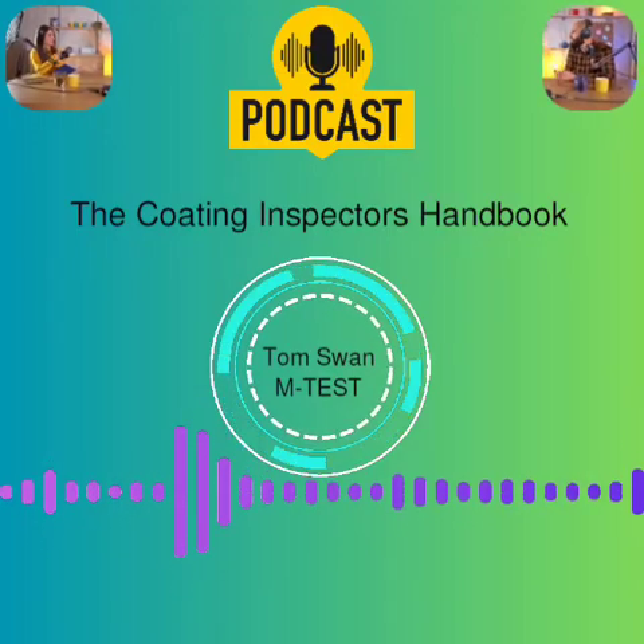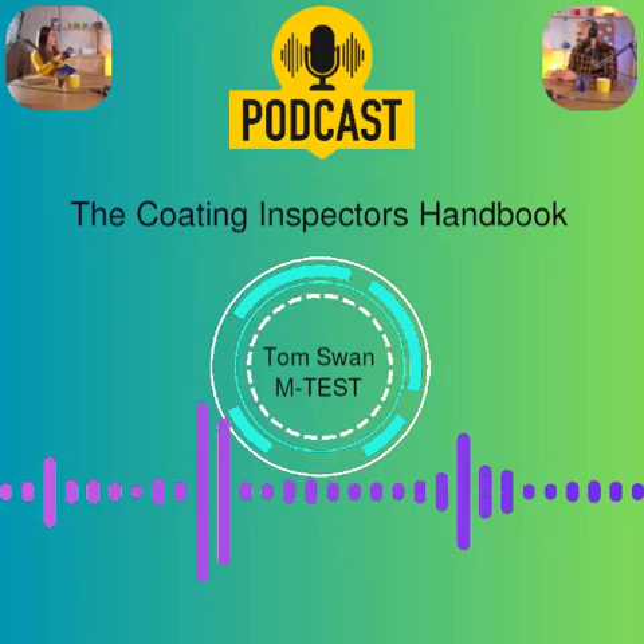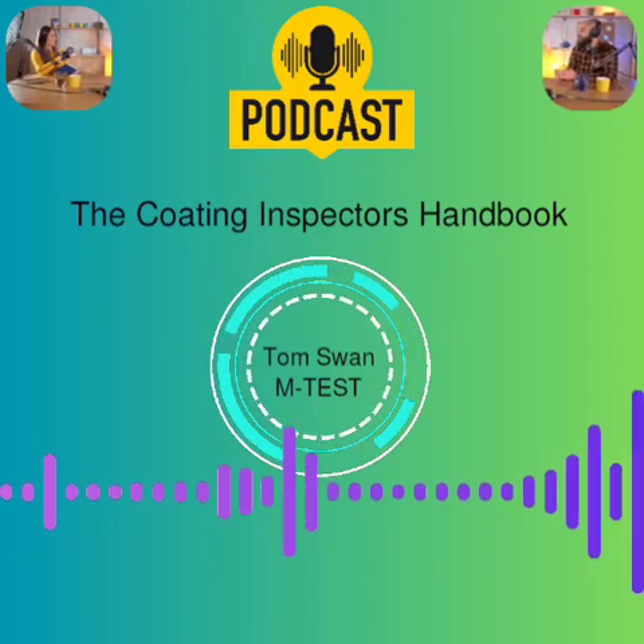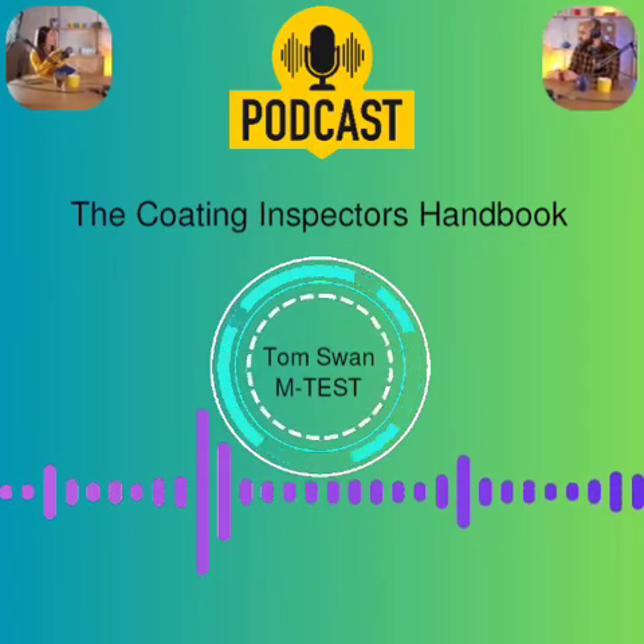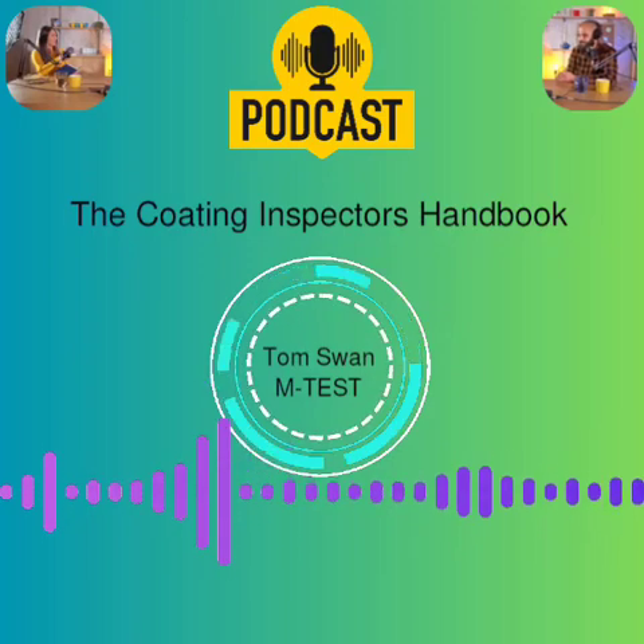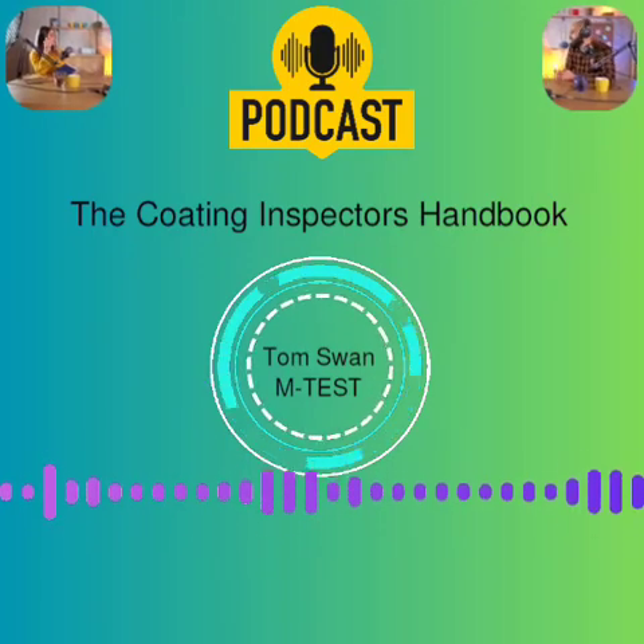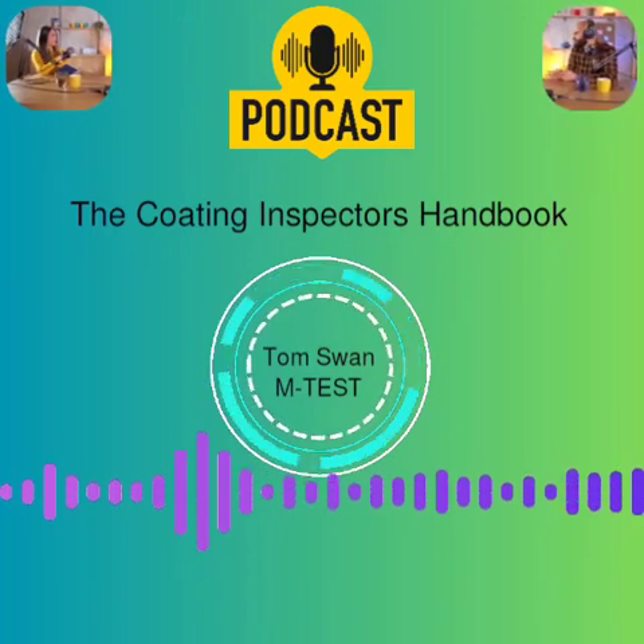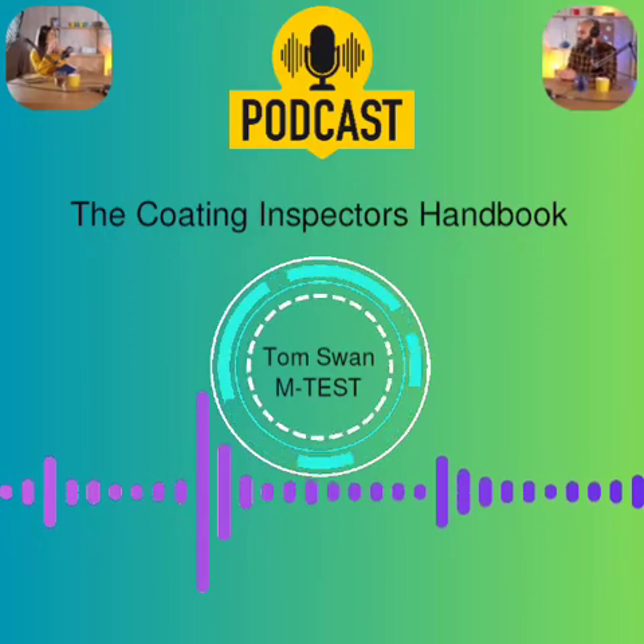And Method C, replica tape. Like Testex tape. It's a special foam tape. You press it onto the blasted surface and rub it really hard. That's called burnishing, to create an impression, a physical copy of the profile. Exactly. Then you measure the thickness of that compressed tape using a special micrometer.